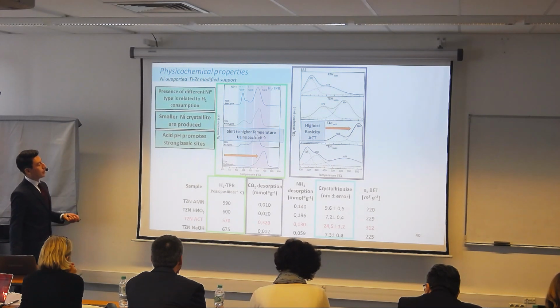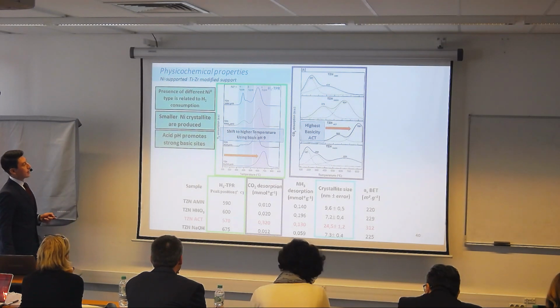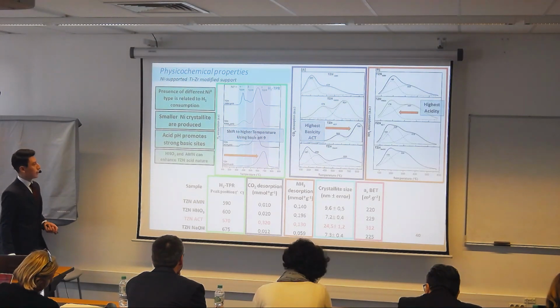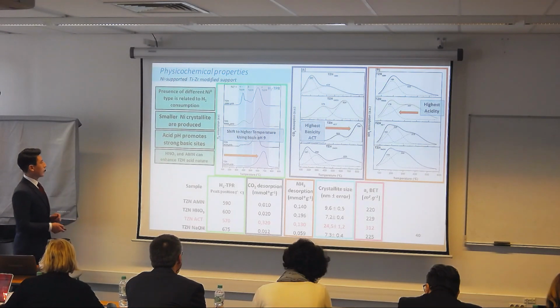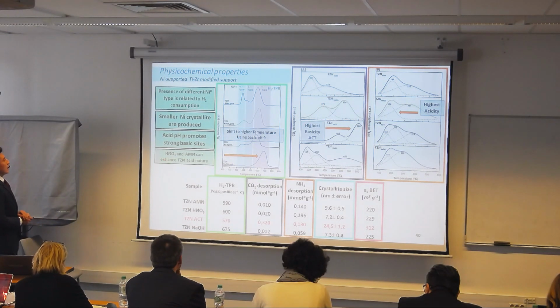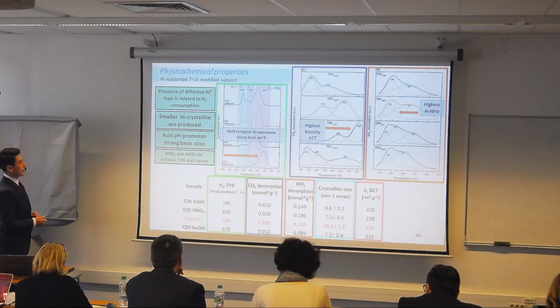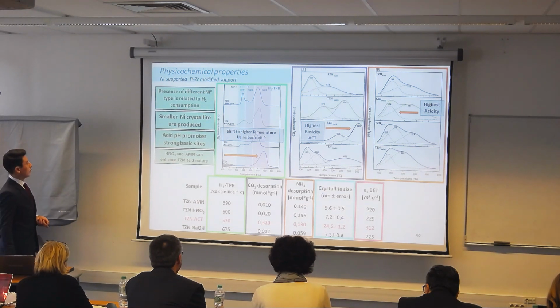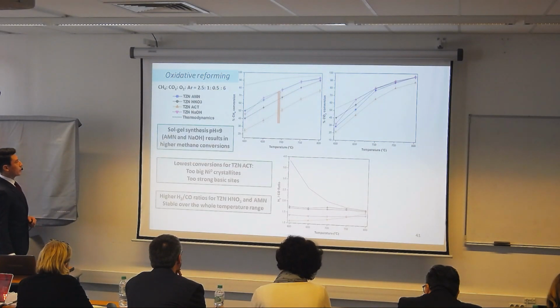About the TPD of CO2, we have the highest basicity when we are using acetic acid. About the acidity, which is an important factor for the reforming reaction, nitric acid and ammonia are enhancing the acidity of the catalyst. You can see here in the table that all of them have very high values compared to the previous ones, and there are no big changes in the surface area between them.